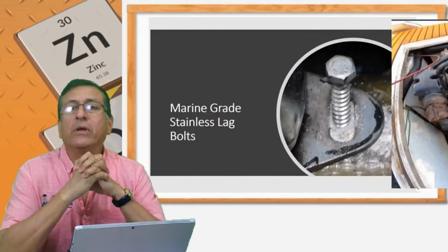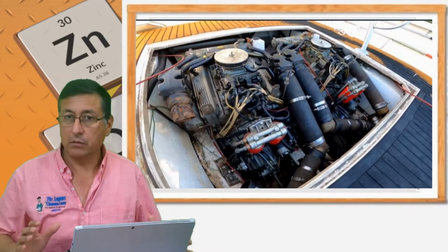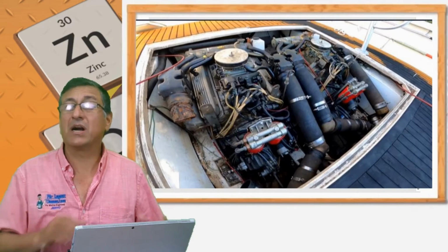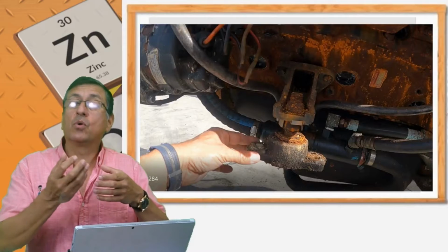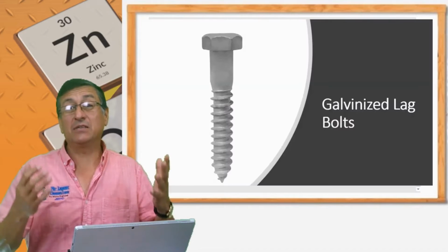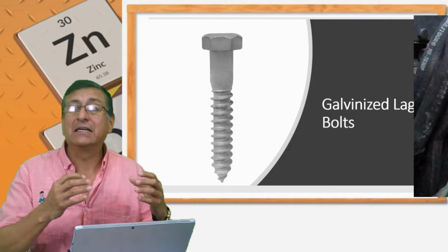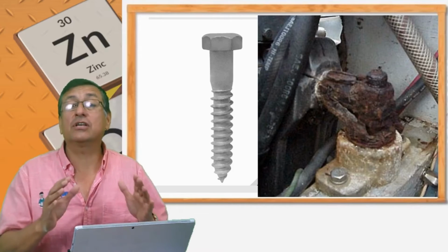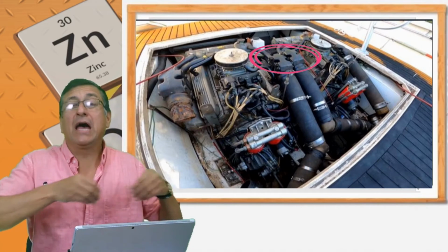With Mr. Rodriguez, we received an inboard boat with two Mercruisers, and the stringers were deteriorated because water penetrated the stringers, because the motor mounts were installed with galvanized lag bolts. The galvanized bolts corroded and corroded the fiberglass, and the humidity entered the stringers and destroyed them. And one engine fell into the second one and destroyed the bell housing.